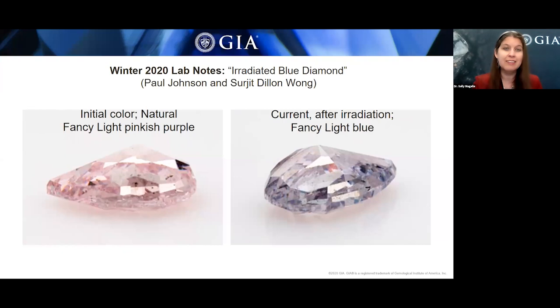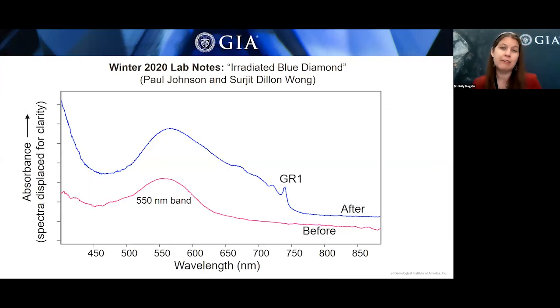The next slide shows visible near-IR absorption spectra collected from this irradiated diamond and compares it with the original natural diamond. The natural diamond shows a broad band at about 550 nanometers, which is typical for this type of diamond, and the pink color is due to plastic deformation that generally occurs deep in the earth. After irradiation, we see the 550 nanometer band and the addition of the GR1 peak and its side bands.